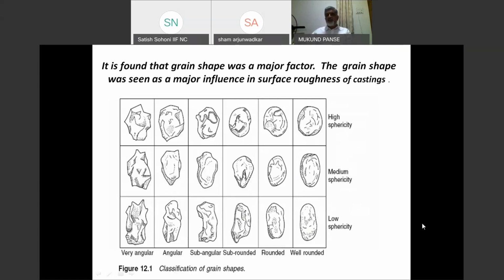The basic grain structure and shape contribute a lot to the properties of molding sand. You seek a rounded grain, so the binder required is less because the surface to volume ratio of a sphere is less compared to all other shapes. However, it is difficult to get an exact sphere. In practice, what you get is subangular to rounded and medium sphericity.